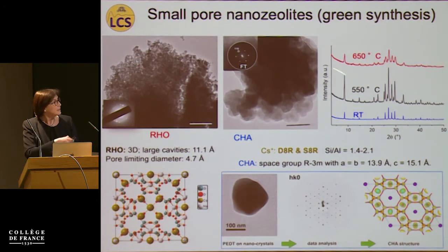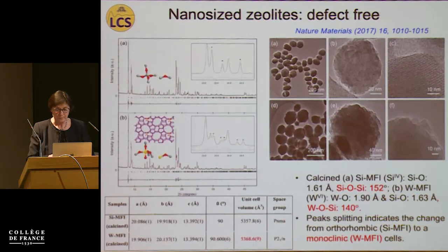And these are some of the examples where we demonstrate that Chabazite zeolite with high stability up to 650 degrees could be prepared just by replacing the organic template with cesium.